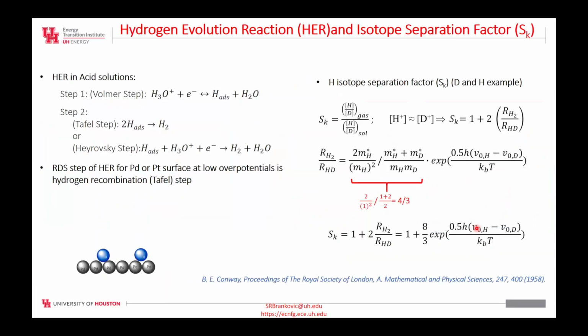Going further, I just want to give you an idea that one of the rate-limiting steps during the hydrogen evolution reaction is the hydrogen recombination on the surface. Therefore, at lower potentials, which is typically the case when you use very active noble metals as a catalyst, the hydrogen recombination is the rate-limiting step, and this step dictates the separation factors between hydrogen isotopes, in this particular case, I'm giving an example between light hydrogen and deuterium, given by this expression where you can see that in the exponent you have the Planck constant multiplied by the frequency of the vibrational bond of hydrogen and deuterium, actually the difference between them. Therefore, if you do anything to the catalyst to enhance the strength of this bond or enhance the frequency, the separation factors will go up. And so if the palladium is extra active, which means it will bind hydrogen stronger, the separation factor should actually be higher.